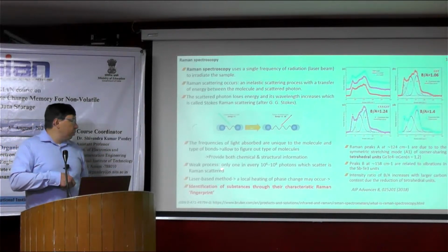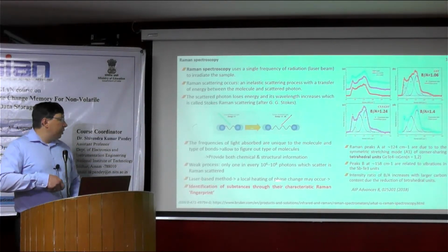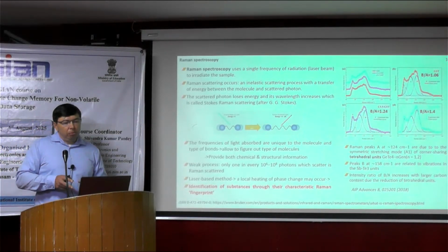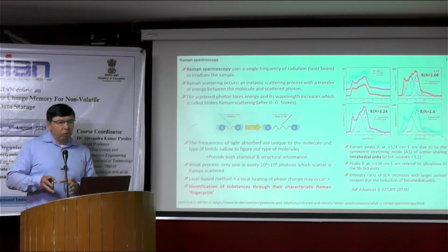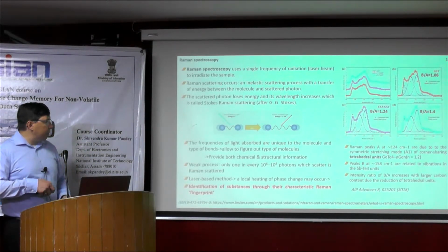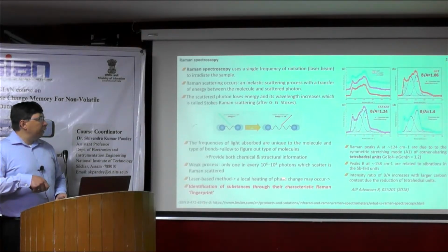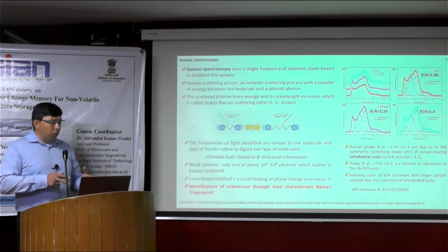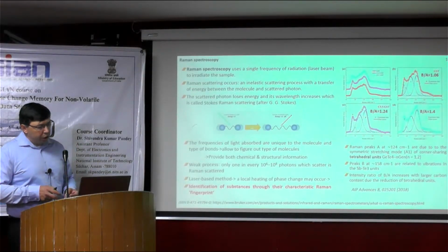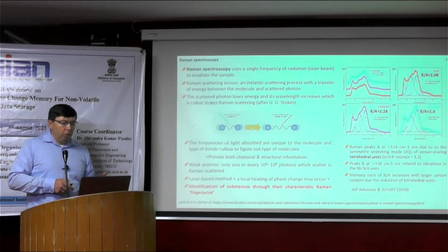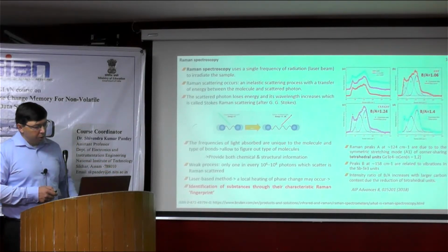So you should play with different laser energies to find the optimum laser energy to study your amorphous materials. For crystalline materials it may not be a big issue, but for amorphous materials you should be careful. You can induce crystallization of your amorphous materials and then study not really an amorphous solid.